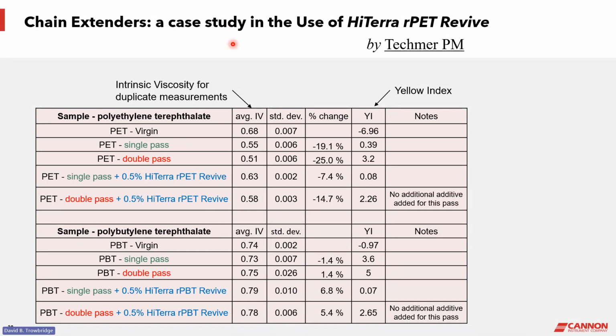I think I may be running low on time, so I'm going to probably have to scoot through these other examples. This is an interesting one. The point here is that, again, they're using intrinsic viscosity with very tight tolerances. Look at the tolerances on these measurements. And they're using them to show how their chain extender, which is protecting the polymer from degradation, is very effective in maintaining high intrinsic viscosities. And again, they use intrinsic viscosity as the basis for their study.